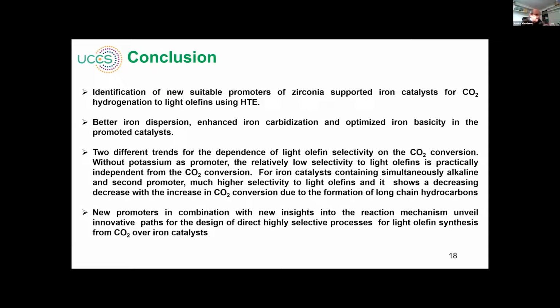We have better iron dispersion, we can have enhanced iron carbidization, and we need optimized basicity, maybe not the highest basicity, but optimized basicity. All of them have higher basicity compared to the reference catalyst, but maybe the highest basicity is not needed. And then we observe two different trends for light olefin selectivity versus CO2 conversion. We have two classes of catalyst, with potassium and without potassium.